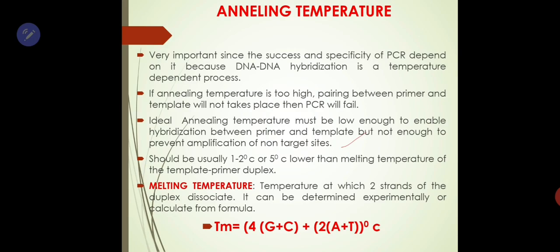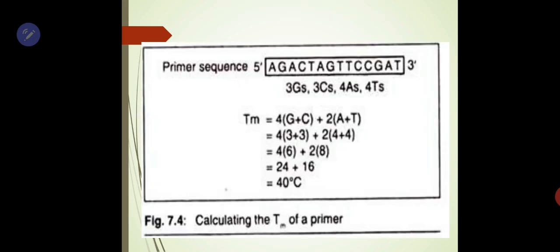So here G, guanine, cytosine, adenine and thymine. So suppose we take a primer sequence containing 14 nucleotides, with 3 guanines, 3 cytosines, 4 adenines and 4 thymines. We can calculate the melting temperature by using the formula, and it can be calculated as 40 degrees Celsius. So we have to calculate the melting temperature of the primer, and we have to set the annealing temperature, the perfect annealing temperature, which is very important for PCR.